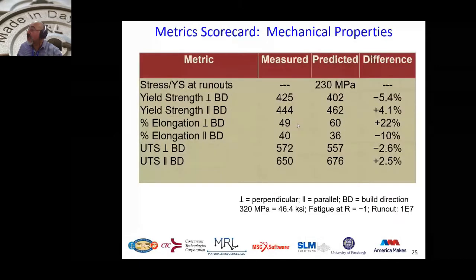We'll show you in the next slide how we met and exceeded wrought properties in this material. So we were able to get stress above the yield, 230, and when we were hitting the yield strength of wrought, we had runouts. For the yield strength of the material, predicted versus measurements, we were within about 5% difference, as well as in the build direction. When we reached UTS, we're within about 3% between predicted and measured.